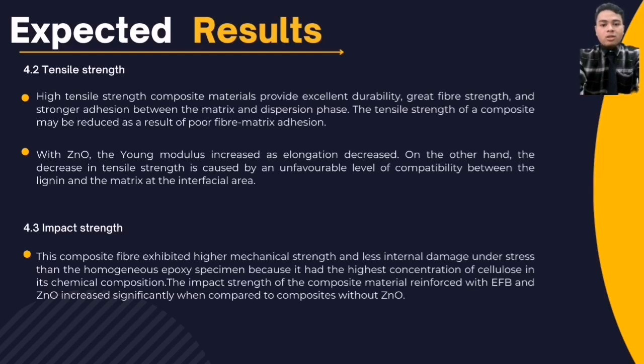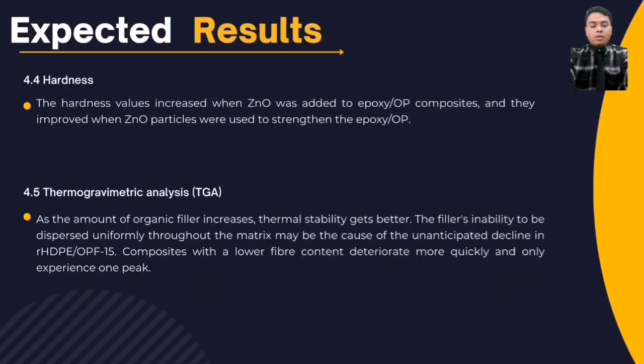4.3 Impact strength. This composite fiber exhibited higher mechanical strength and less internal damage under stress than the homogeneous epoxy specimen because it had the highest concentration of cellulose in its chemical composition. The impact strength of the composite material reinforced with EFB and zinc oxide increases significantly when compared to composite without zinc oxide. 4.4 Hardness. The hardness value increased when zinc oxide was added to epoxy and oil palm composite, and they improved when zinc oxide particles were used to strengthen the epoxy and oil palm.